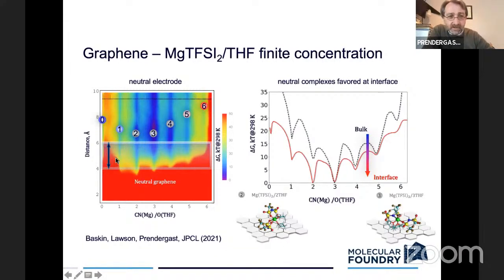So this is a two-dimensional free energy landscape where the heat map shows the free energy, the scale here on the right. And we've got coordination number of different species, magnesium with the solvent, and distance from the electrode on the vertical axis. So each of these narrow minima or wells within this free energy landscape, those represent countably different species that exist. So let's say if I have fourfold coordination with the solvent, that means in this case there's either 1 or 2 points of contact with an anion. Sixfold coordination, there's no anion. You see that one is really shallow, so it's very unlikely that you get those species. And there's a lot of contact ion pairing and tripling and so on.